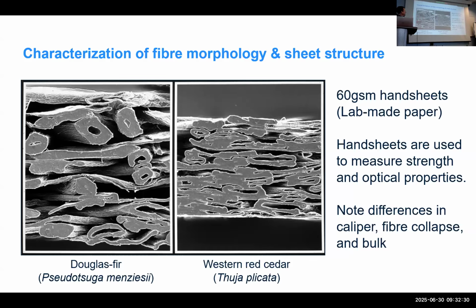Here, looking at morphology, again characterization, these are laboratory-made papers that we use to evaluate strength and optical properties, and then we can also examine them microscopically to correlate the physical test data with the morphology. These are 60 gram per square meter hand sheets, so that's the mass per unit area. It's the same between these two sheets, exact same magnification, and all that's different is the wood species. So Douglas fir, a prime lumber species, known for having very thick cell walls, less collapsible, versus Western red cedar, which is very large diameter, thin walled cells.